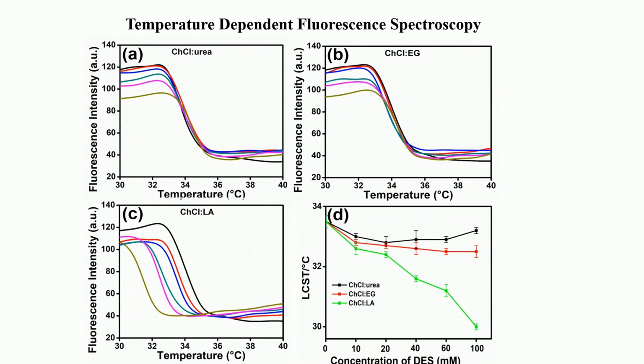Temperature-dependent fluorescence intensity measurements were carried out using an external fluorescent probe, that is ANS. The intensity of ANS in the PVCL aqueous solution changes sharply once the temperature reaches the critical transition temperature. The figure clearly shows the variation of transition temperature in the deep eutectic solvents, which depends on the type of hydrogen bond donor group present in the test molecules.